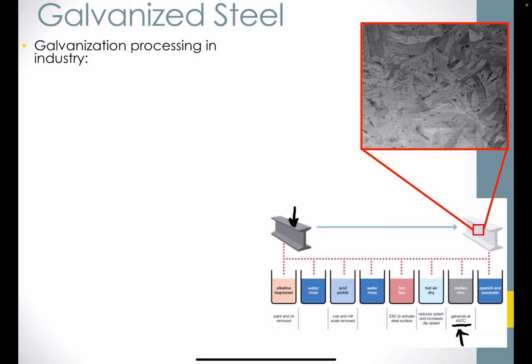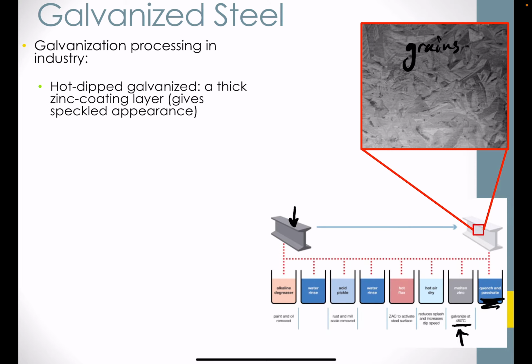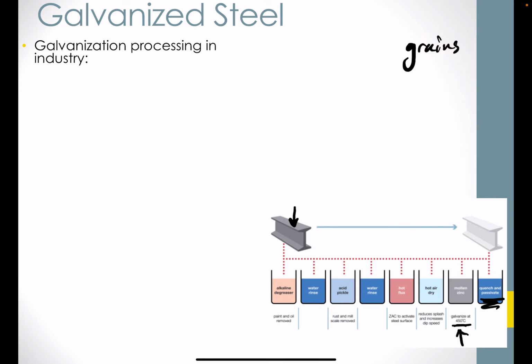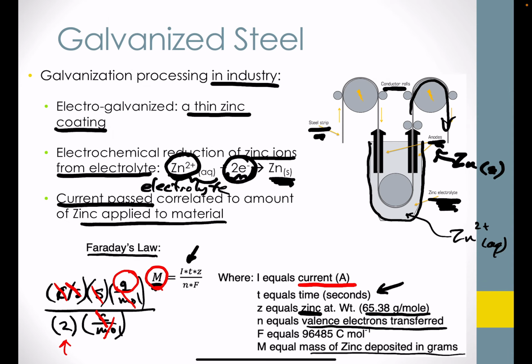Again, the final structure here is going to be rich in excess zinc, and so we'd expect pure zinc to exist at the surface with grains owing to the crystallization of that zinc after the quench step, typically executed by a water dip. So the hot dip method generates a thick coating of zinc to contrast what we saw in the electrogalvanization process, which typically generates very thin coatings governed by the Faraday's law.